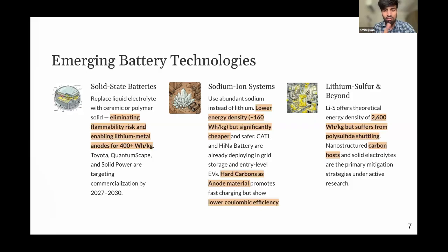used for capacity. So we need to solve this problem with lithium sulfur, and nanostructured and nanocarbon hosts are the real game changer. People have researched it for more than 10 years now. We need carbon hosts which can house these small sulfur particles to prevent dissolution into the electrolyte and prevent the polysulfide shuttling effect. But lithium sulfur is a chemistry which needs at least 5 to 7 years to come to a stage where it can be developed at a cylindrical commercial level.